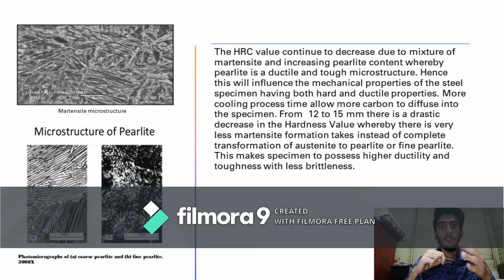From 12 to 15 mm, as we can see from the table, there is a drastic decrease in the hardness value. There is a very major difference in the hardness value. This is probably due to very little martensite formation taking place during that stage. Instead, there is more transformation from austenite into fine pearlite. This makes the specimen possess higher ductility and toughness with less brittleness.